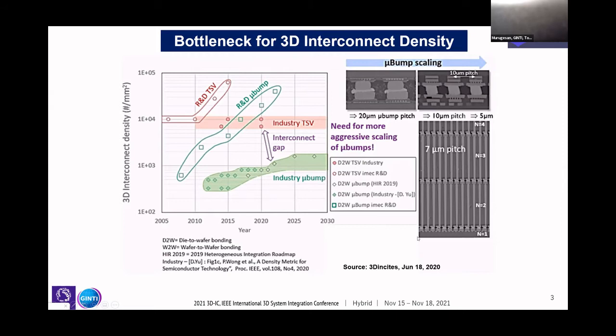Although we have been able to move from several tens of micrometer bump pitch, I'm talking about the bonding pitch, to a few micron pitch, this is so far so good only when you are talking about flip chip. When you are going to stack, even though we are able to reduce our TSV size to a few hundred nanometers or, if not, a couple of microns, your micro bump bonding pitch is still somewhere between 7 to 10 micrometer. So basically the bump size limits the interconnect density in the 3D stacked system. So how are we going to reduce our 3D interconnect bonding pitch?